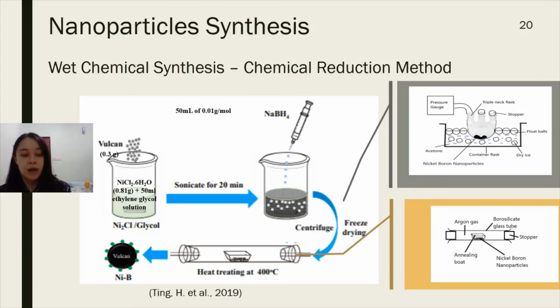First, we will add the Vulcan into dispersed nickel chloride solution with ethylene glycol solution and add drop and undergo sonication. After that, dropwise of sodium borohydride will be added into the solution and then undergo centrifugation. After that, we will freeze dry the nanoparticles using a triple neck flask connected to a pressure gauge and immersed in a dry ice. So after that, we'll undergo heat treating where it will be purged with argon gas.